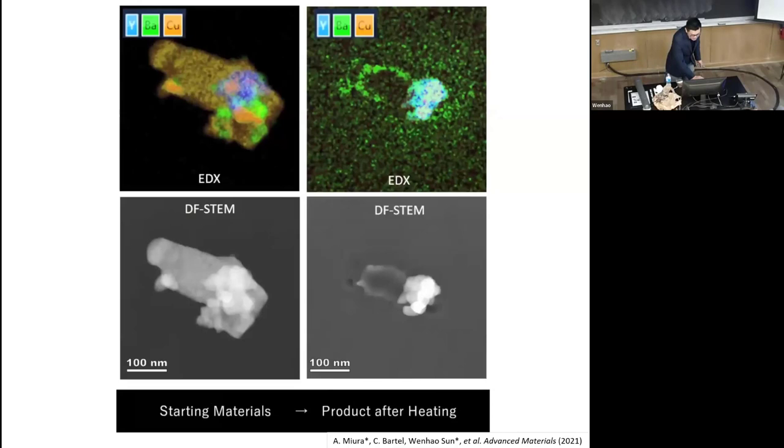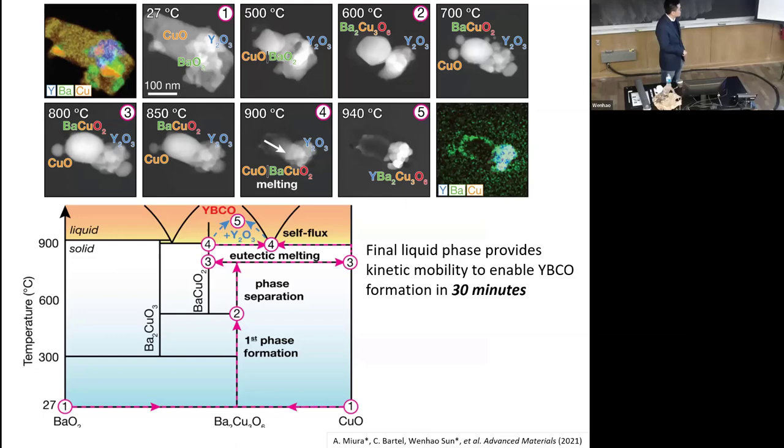Okay, so what we're gonna look at now is the phase diagram. If we look at the phase diagram around barium peroxide and copper oxide, the important thing is that yes, indeed you form barium 2 copper 3 O6. That's what we predicted from the reaction energies. But what's really cool is that the reason why this system can form YBCO is that